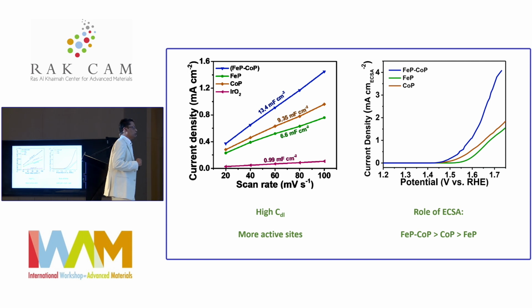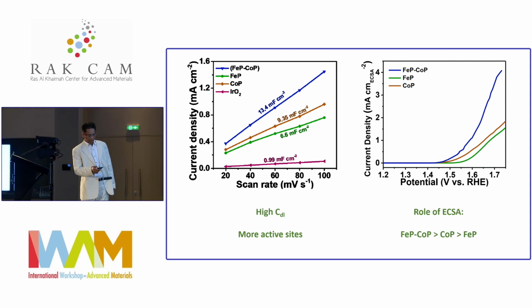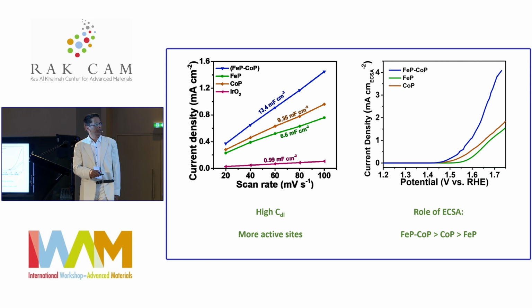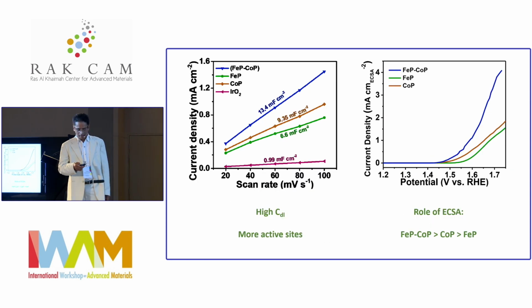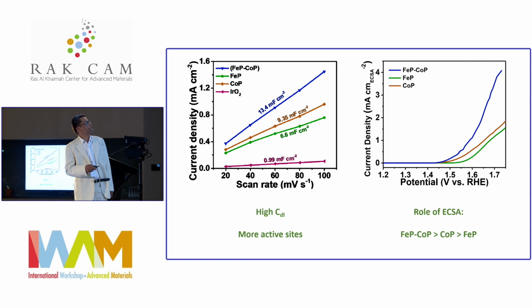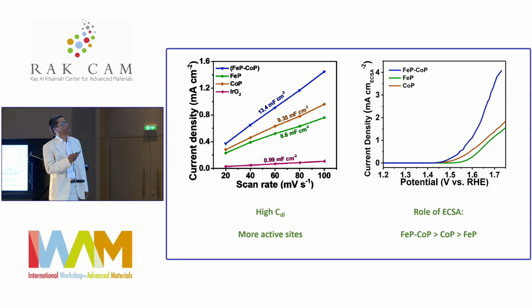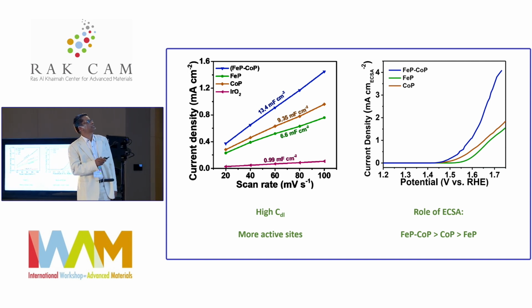And to look at the electrochemical active surface area by double layer capacitance, you can see that compared to cobalt phosphide and iron phosphide, which are around 8.6 millifarad per centimeter square, the mixed iron phosphide and cobalt phosphide at 0.8 iron and 0.2 cobalt, by weight percentage, cobalt is 20% and iron is 80%, shows almost double the double layer capacitance of the FeP.